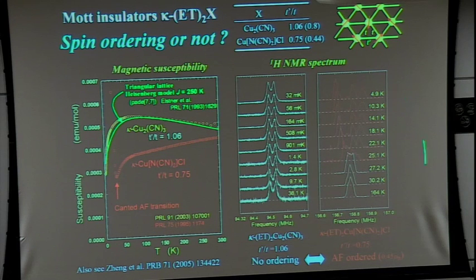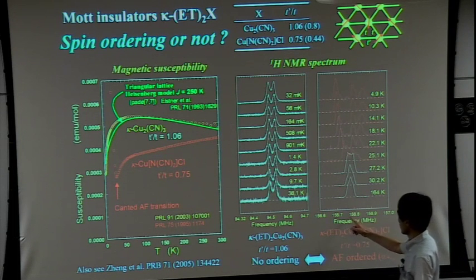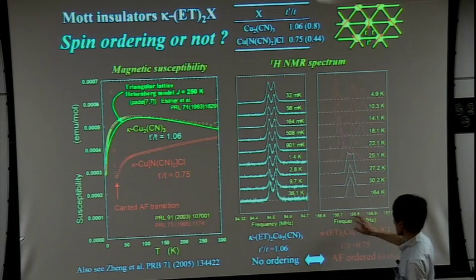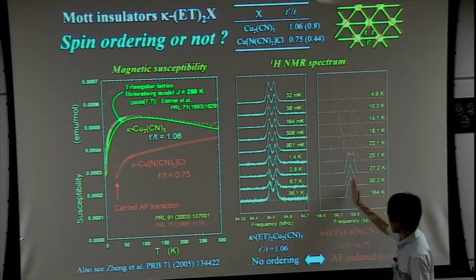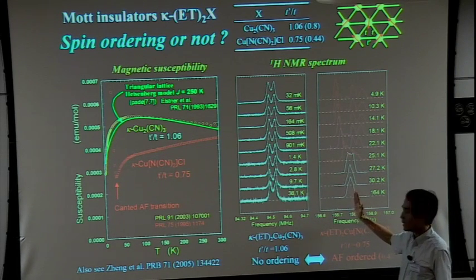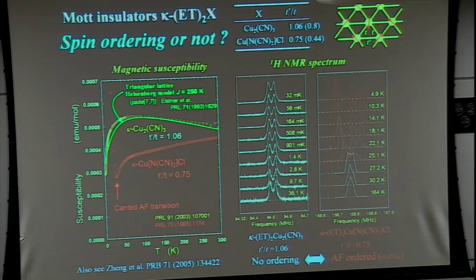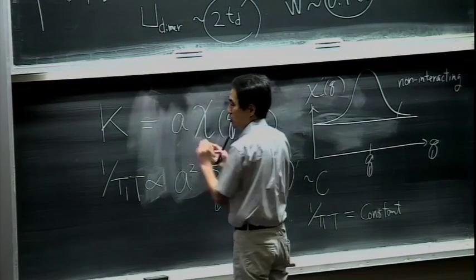Please take a look at the NMR spectra. In the less frustrated case, the magnetic transition occurs around 30 Kelvin, so the NMR line shows a single peak at high temperatures, at 156-something megahertz, corresponding to the external magnetic field. In this case, the proton NMR coupling constant is very, very small, so in the paramagnetic state its Knight shift is not resolved.